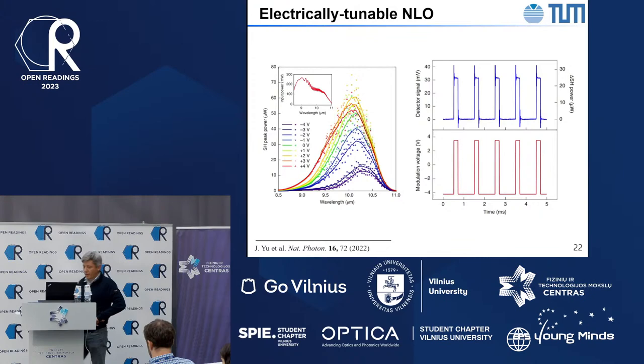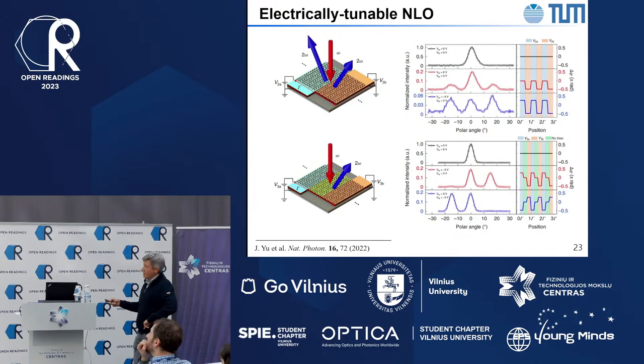You could also do tricks by biasing the structure continuously and then introduce the continuous variation of the phase of the nonlinear response. And here you have these antennas, and here's one bias voltage, here's another bias voltage, and then the structure is repeated many times to the side. So when the bias voltage is the same, you have a uniform structure. Angle of incidence of your pump, which is normal, produces the normal output of second harmonic generation. You apply bias selectively to the structures, and then you introduce variation in chi2. Essentially, you create a grating. And then in the output, you start seeing the diffraction orders, because now chi2 is non-uniform across the structure.